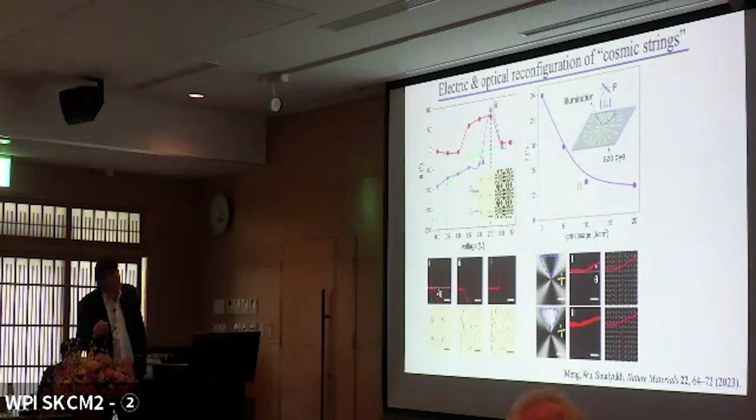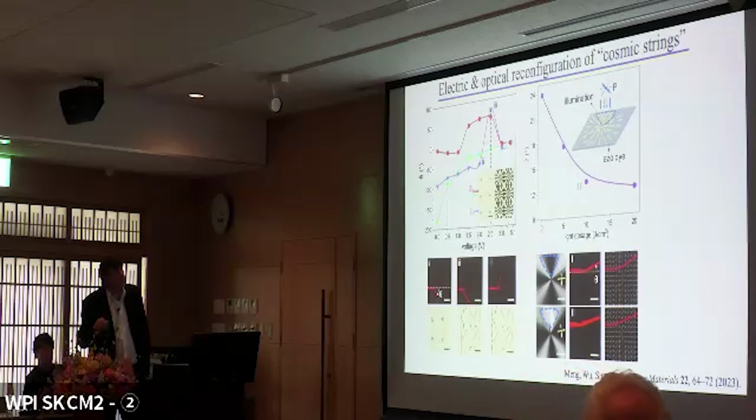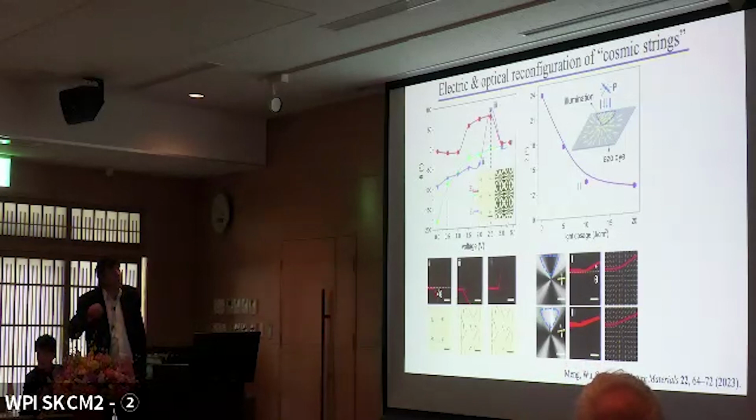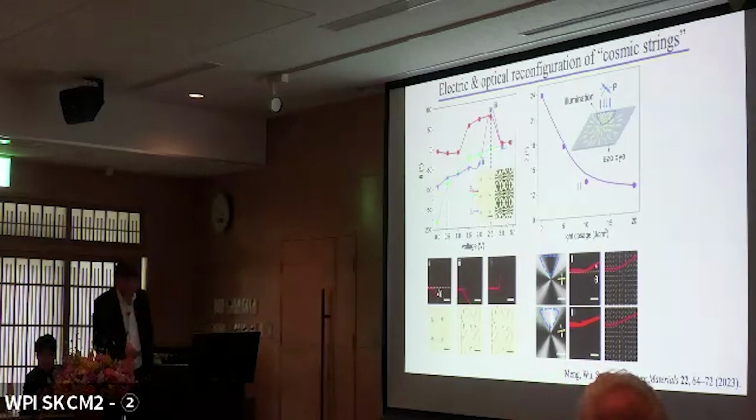So, for example, the deflection angle of light due to its interaction with these vortices in the arrays can be controlled by applying electric field and effectively stretching these vortices, as you can see in here. And so by just changing applied voltage within a range of up to 3 volts, you can see we can steer beams in a very large range of steering angles.